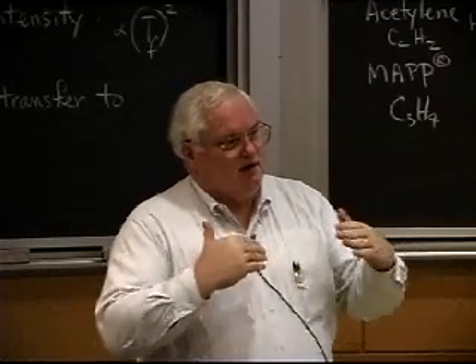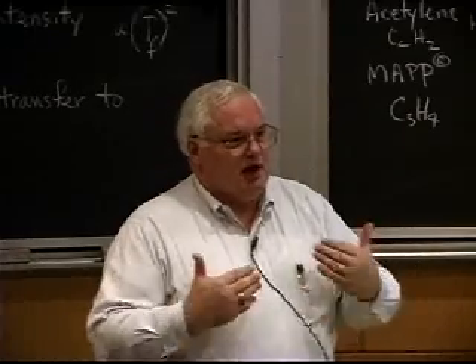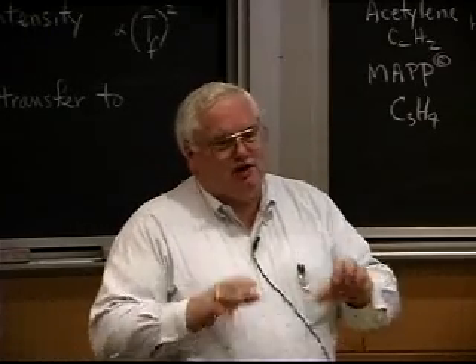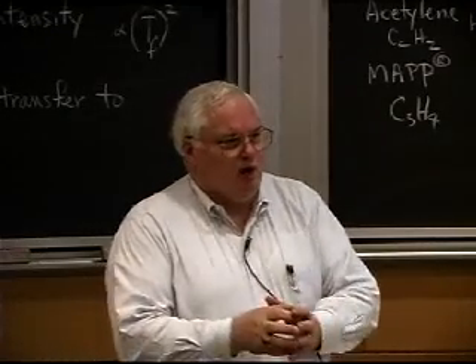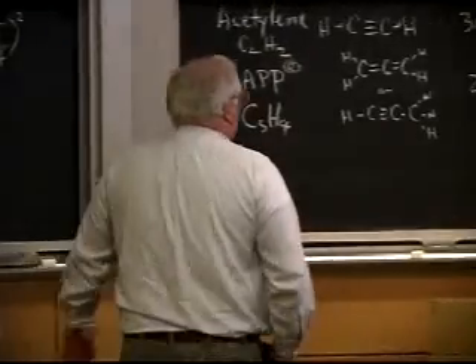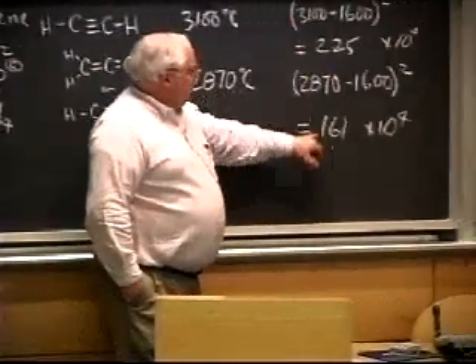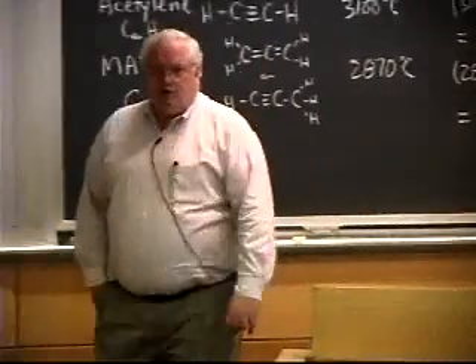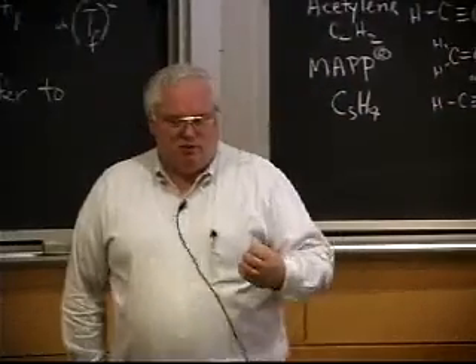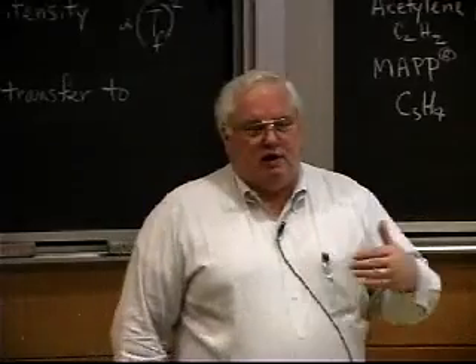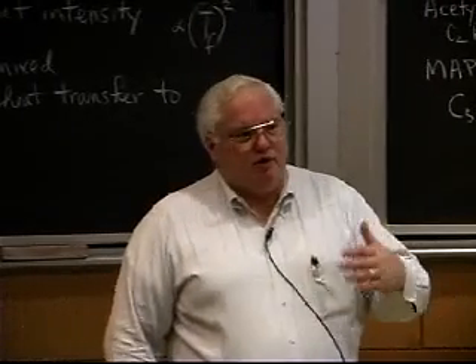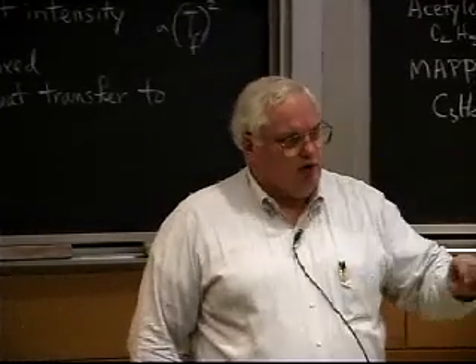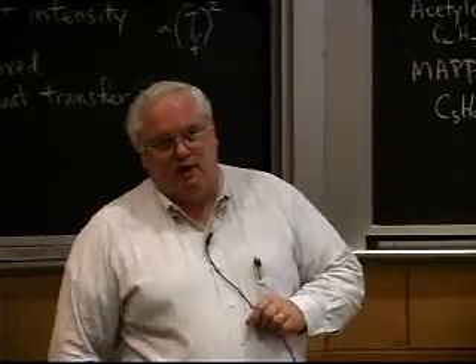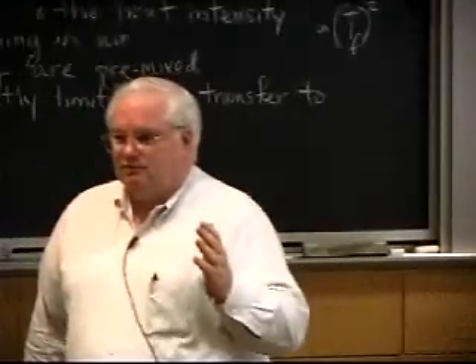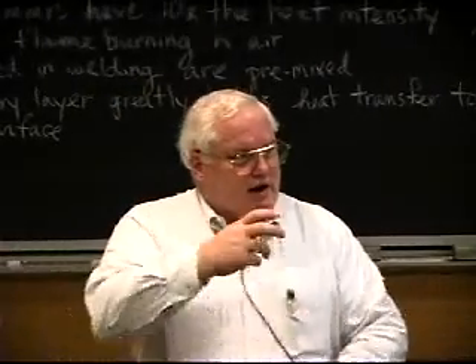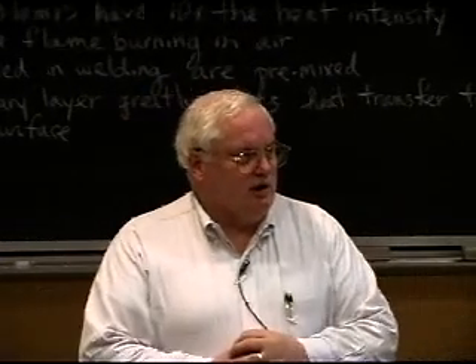But when you start trying to heat up something that's already hot, namely the liquid weld pool, your ability to transfer more heat into the molten weld pool is limited by the upper temperature of the gas that you're trying to use, and so that small difference in temperature has a big effect on your ability to weld. If you're using oxyacetylene, you can probably weld about 30% faster in terms of traveling along the weld pool as you can with MAPP gas. So why does anybody use MAPP? Aside from the fact that you can buy these nice little handy cylinders like I had, you can burn down your house easier.